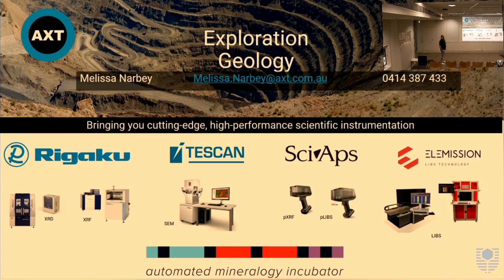Does that change the mineralogy? Yeah, it does. When we first started looking at some lithium core, because we'd done a lot of SEM work, we had all this sodium and potassium in the spodumene. It's like, this is really weird. And then we just washed the core and it all disappeared. That core came from an area that had hypersaline water, and the water that had dried on the sample was really messing up our mineralogy.